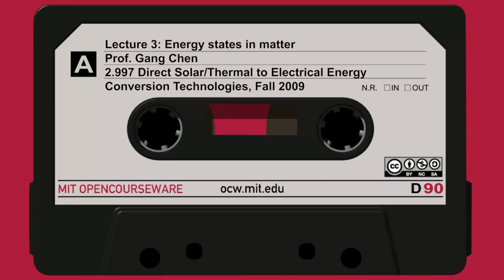And now the F, I'm going to just ignore the 1 plus 1. That's a Boltzmann approximation to the Fermi-Dirac distribution. So I plug in this F already here. So that's my number of electrons in this region, in the conduction band. I encounter this classical problem.